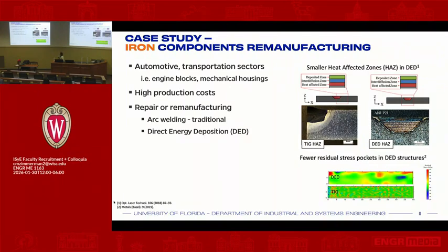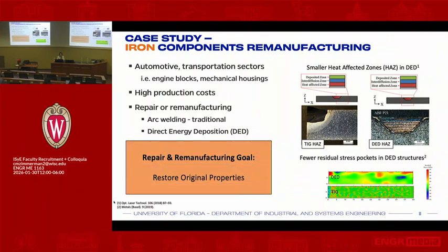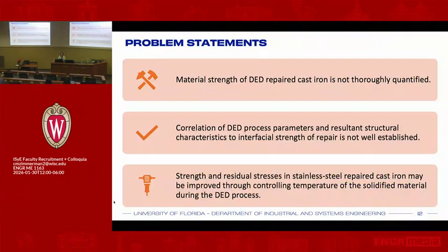But when you look at a DED heat affected zone, you can see that it's very thin. It's also more controllable, if you see how it is the same width throughout the whole repair. And when you look at the stresses too, you're going to see that the stresses are more associated with pockets in certain areas instead of distributed all throughout the tensile region. So there are some reasons to consider that. And with that said, I'm putting that into your mind with the ability to restore original properties. Here are some of the areas that are still needed to do repairs at that large scale.